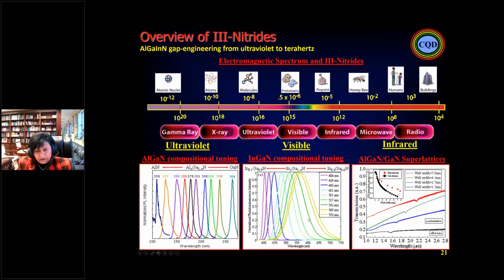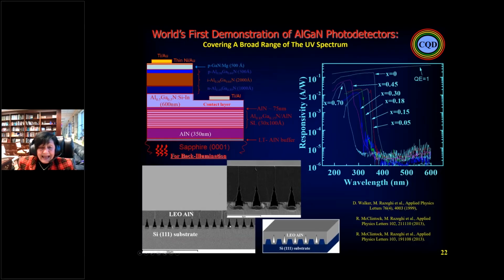That is the photoluminescence. Exactly as you can see, we can go from 290 up to the visible, 400, and by intersubband we can go up to the terahertz. So after that is the growth of this material. That is very important: how we can now make the LEDs, lasers, and detectors. That again is the theory, the quantum mechanics, the confinement and optimization of the structure. So you do the optimization, that is the theory part, not the growth, and that is the growth exactly as you can see here. I put that here on silicon substrate.